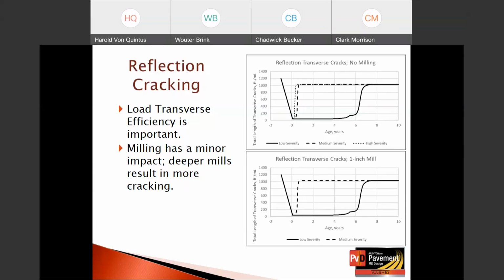Okay, this now shows the reflection cracking for transverse cracking. Again, load transfer efficiency is important. The solid black line on the top is for low crack severity transverse. The longer dashed line is for a medium severity crack transverse. The short dashed line is for high severity.